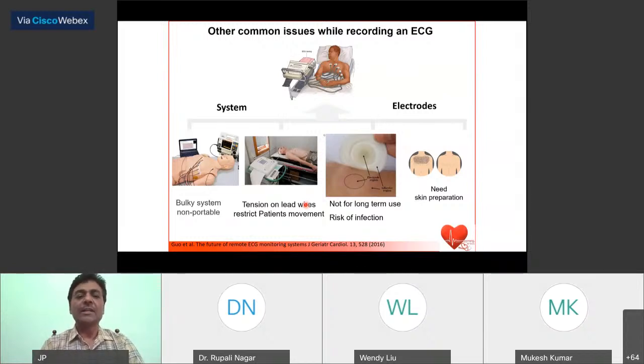And also for long-term heart monitoring, it is not possible to use this kind of system, which is bulky. And one of the biggest problems with this gel is that for long-time use, the gel solidifies, and its impedance also increases a lot. So there are a couple of problems with the current ECG electrodes and systems.